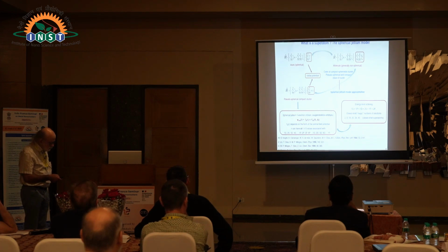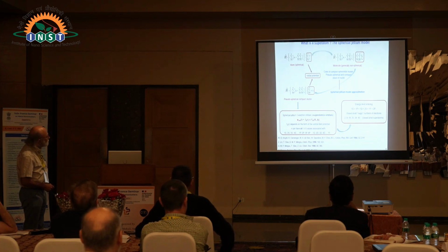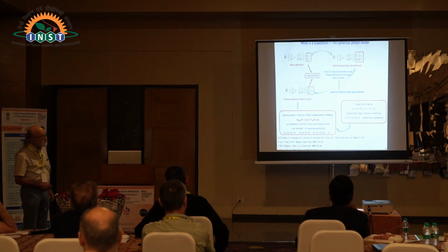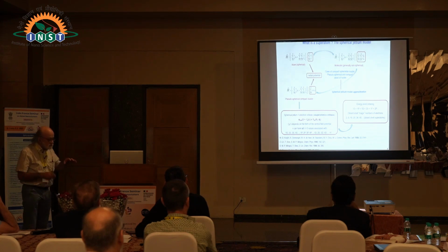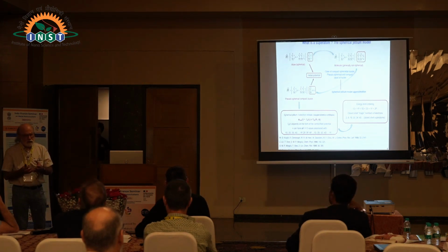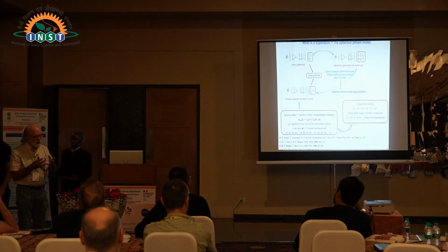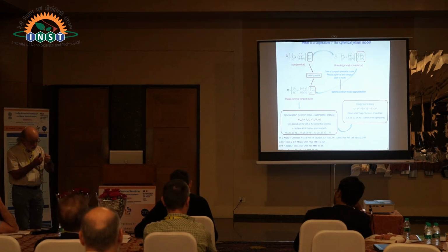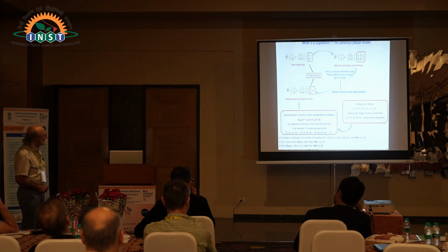Now, let's go from an atom to a molecule. What is changing, of course, we have now several nuclei. So we have a sum not only on the electrons, but also on the nuclei, and we lose the spherical symmetry. But let's consider a spherical or almost spherical molecule. If this spherical molecule is also compact, made of metal atoms, for example, which are associated in a compact way, then we can make an approximation which is called the spherical Jellium approximation.